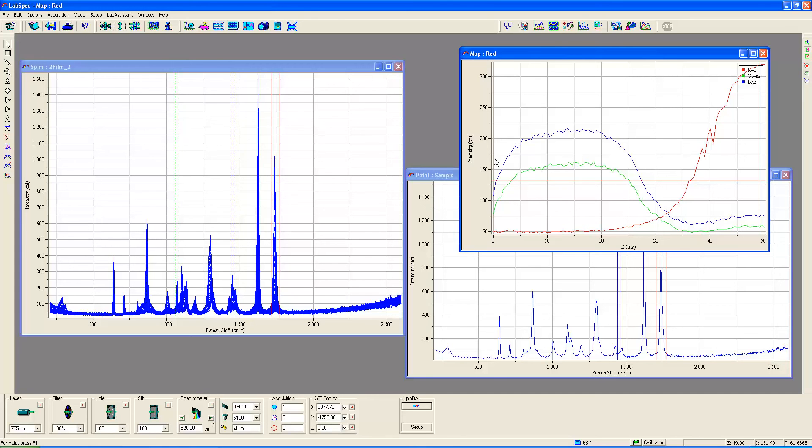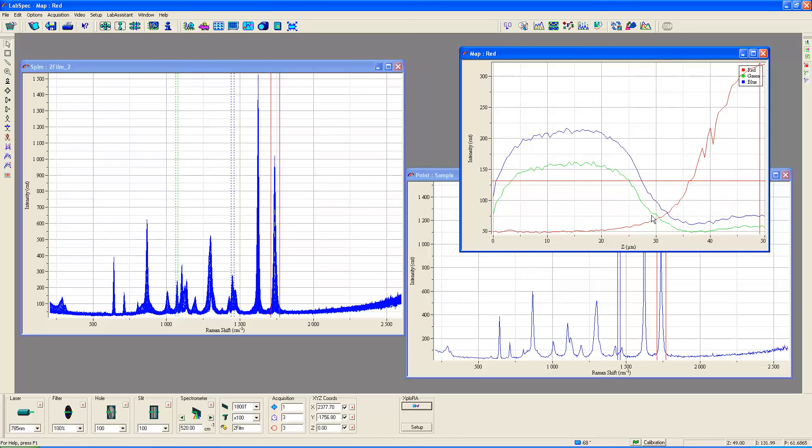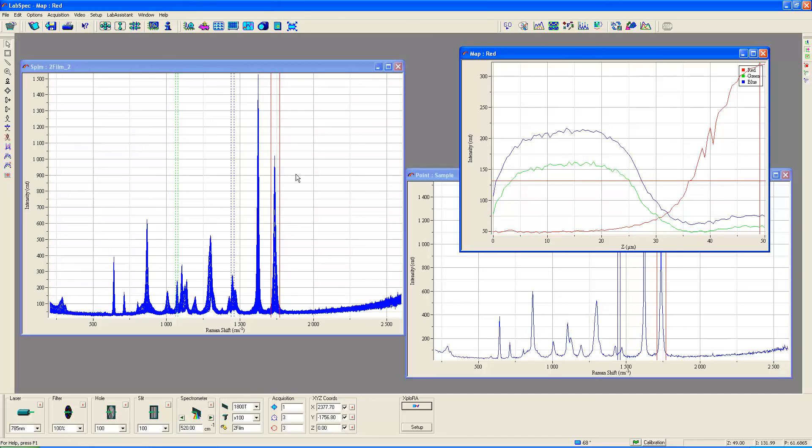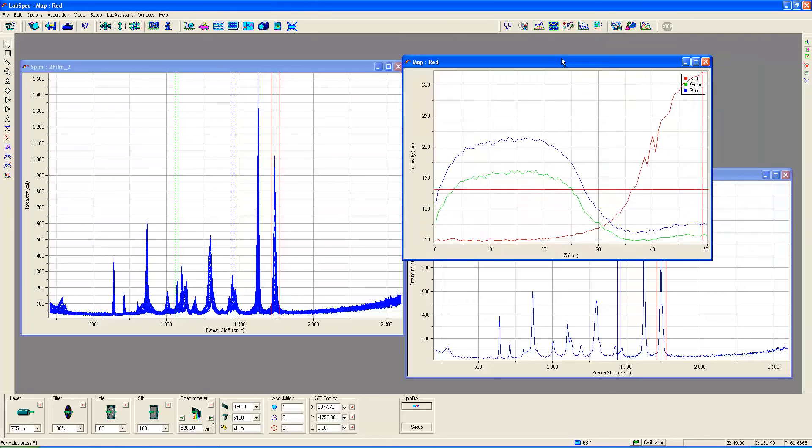What we see is that if we segregate off the peak areas associated with the polyethylene, then the polyethylene is strongest from approximately two and a half once the beam is fully into the film to around 35 micrometers or so. So this film is probably approximately 30 micrometers. Once the focal plane starts moving down through the polyethylene then we start seeing the onset of the peak associated with the polyethylene terephthalate. You could generate a depth profile just from tracking the peaks associated with the different chemical compositions.